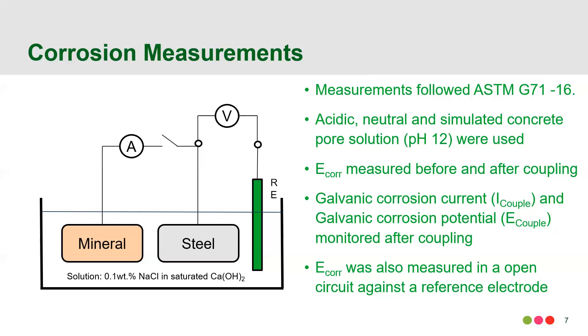We had different solutions in terms of pH, so we used an acidic, a neutral, and a simulated concrete pore solution. That was because, given that the pyrite corrosion process produces sulfuric acid, it's not entirely clear where the pH in an active system would lie — whether the acidic sulfuric acid would predominate or the pore solution. Similar results were seen in all cases. We're going to show the results from the simulated pore solution. The corrosion potential was measured before and after the switch was closed to couple the samples together. Then the galvanic corrosion current and the galvanic corrosion potential were monitored for a long period of time after coupling. We also measured the corrosion potential in an open circuit against a reference electrode, and those are the examples we're going to show first.